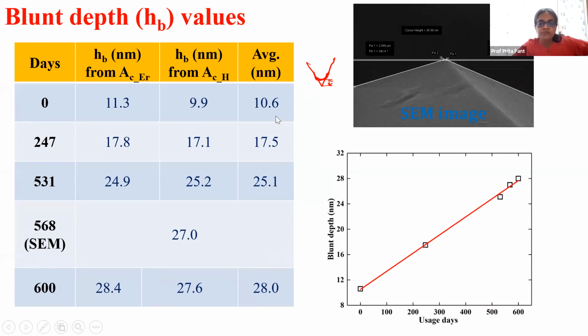This depth goes from 10 nanometers to 28 nanometers in a space of about 600 days. So it's over a 50% change, but it is occurring over a period of about 2 years. Please note this includes lockdown, so this is an underestimate. This is the same thing shown as a plot, and Prakash was also brave enough to then take the tip into an SEM.